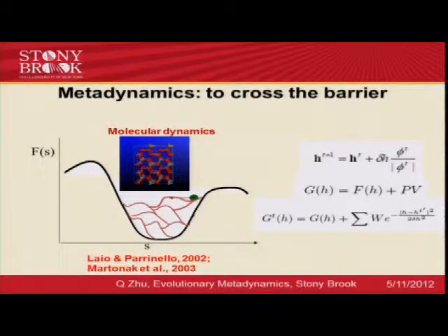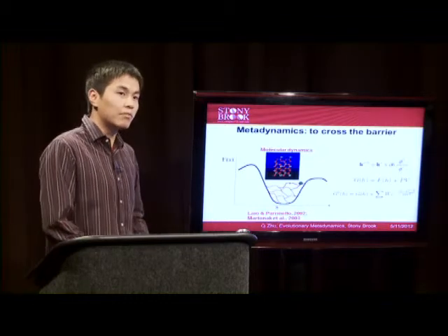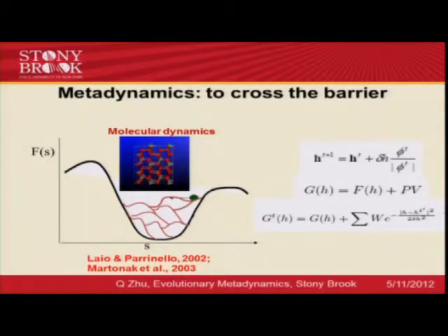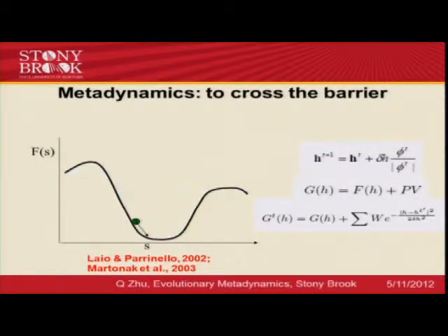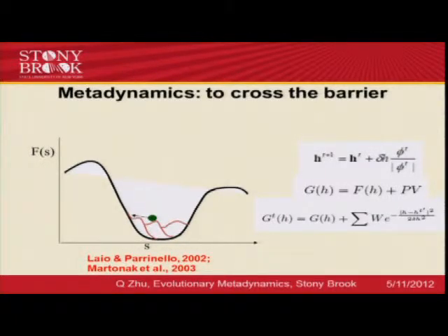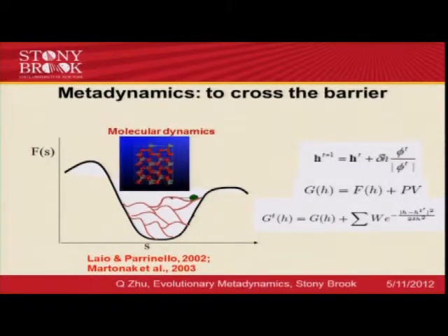Metadynamics provides a possible solution. The idea of metadynamics is to study pressure-induced phase transitions. It uses the cell edges as a collective variable and then constructs a new energy term called the Gaussian function. The Gaussian function is history-dependent. By introducing this history-dependent Gaussian function, it can drive the system to gradually get out of the trap of energy minima until the phase transition happens. At each step, the system should be equilibrated by molecular dynamics simulation.